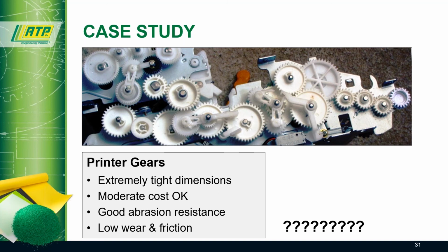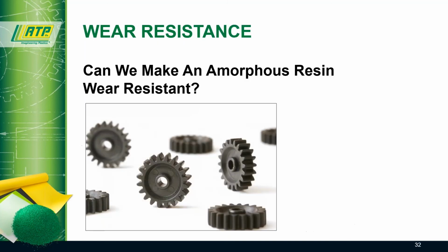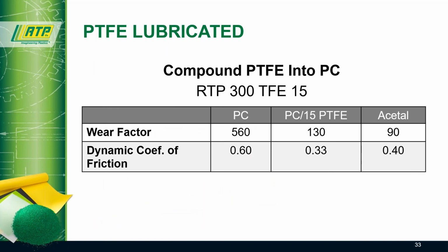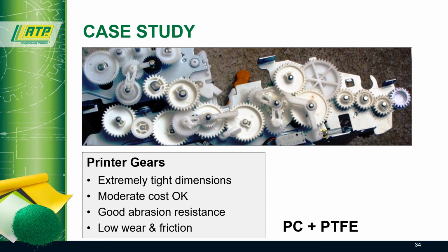So let's dig into the wear properties. The question here is, can we make an amorphous polymer, which has the dimensional stability, more wear resistant? One way to accomplish this is to compound a wear-resistant additive, such as PTFE, into the amorphous resin. As shown here, polycarbonate can be made to have similar wear and friction performance as compared to acetal by compounding 15% PTFE into this polymer. So, if we go back to the printer gears, we can address the conflicting morphology requirements with a PTFE modified polycarbonate.